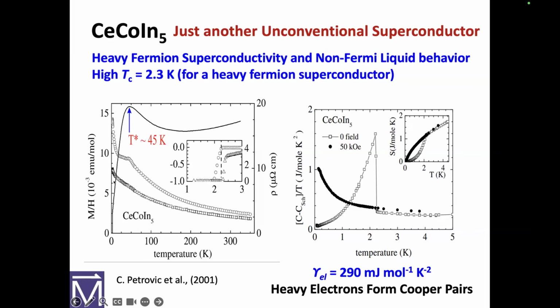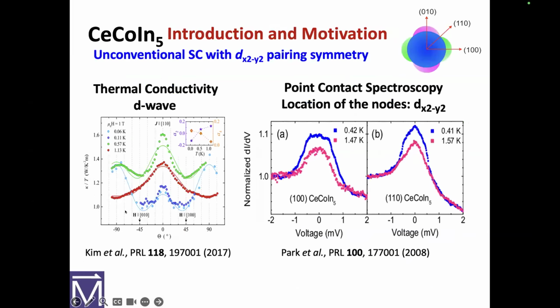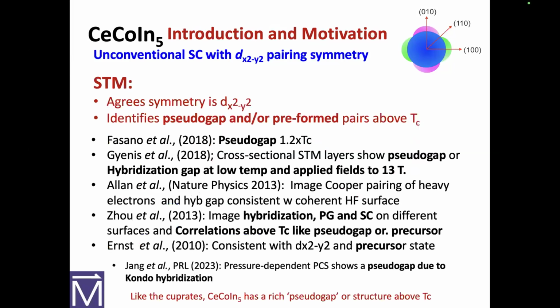So this is the Kondo lattice effect, and Tc is down here. We use point contact spectroscopy to show us d_{x²−y²}. It's been accepted, and this is a very rich slide with a bunch of references in it, which is that there's a bunch of STM out there that agrees that it's d_{x²−y²}, and they also describe either a pseudogap and/or preformed pairs.